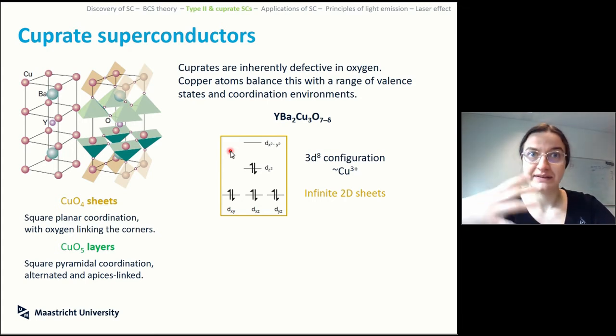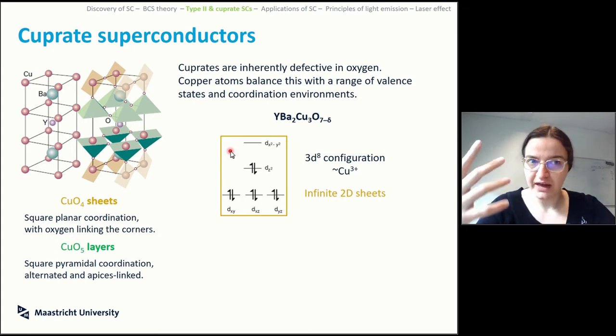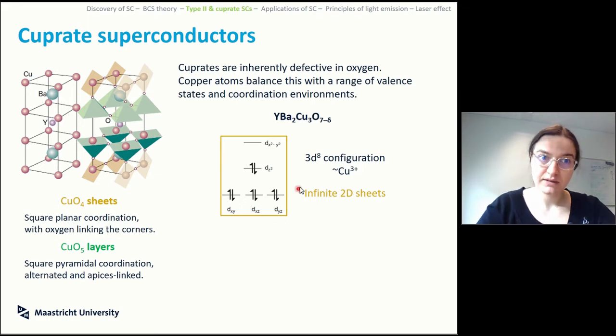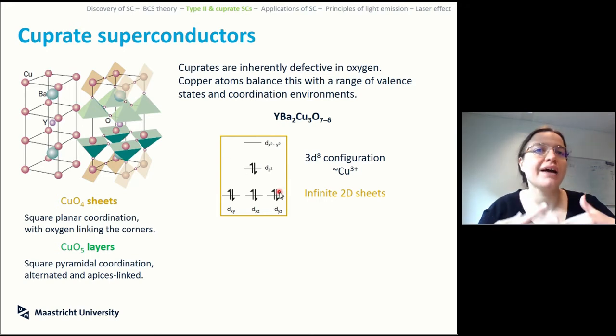So your copper is a 3d atom. You will have 5 different d orbitals. The best arrangement of the d orbitals to have a square planar coordination is this one, and the most stable oxidation state that you must have is the d8, because it fills up everything and it leaves one completely free. So this means that this thing should be roughly a copper 3+.